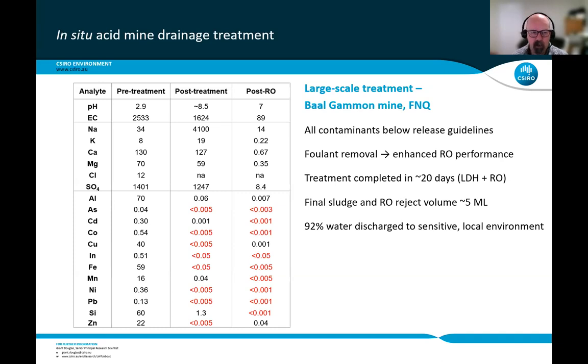The other important thing was the final sludge volume and the RO reject volume was around 5 megalitres. That meant that we were able to discharge over 92% of the water to the local environment within 20 days. So that's really quite phenomenal, that we're able to get in and treat what is a really nasty lot of acid mine drainage water and discharge it within 20 days.